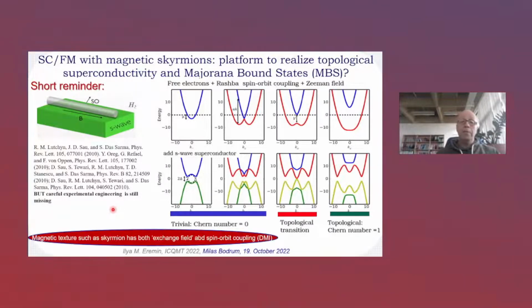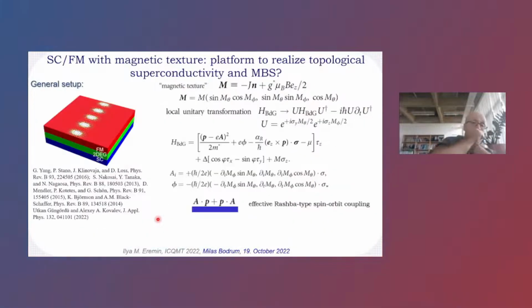So now let me tell you that here you have basically a magnetic exchange field and a spin-orbit coupling, and in principle, magnetic textures like skyrmions have both. They have an exchange field, which is much larger than just an external magnetic field, and you also have an intrinsic spin-orbit coupling like the Dzyaloshinskii-Moriya interaction, which basically tells you that such a skyrmionic texture can be an interesting platform to realize topological superconductivity. And this was the reason why people also started to look into this.